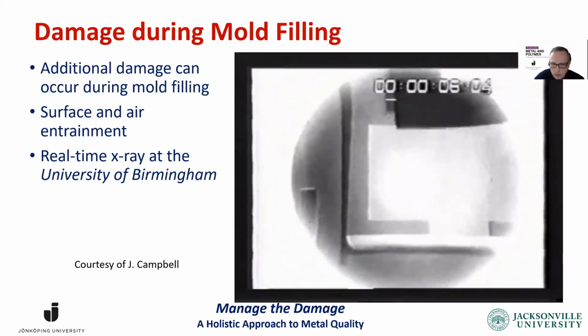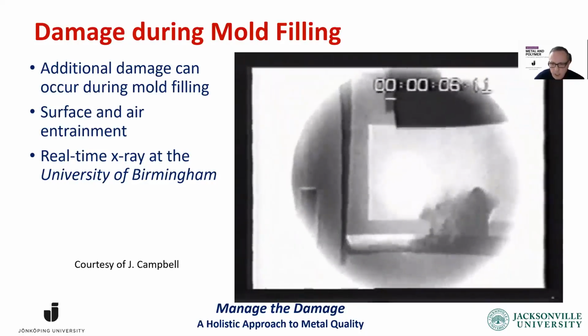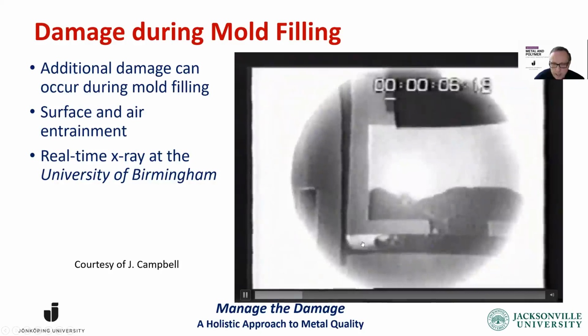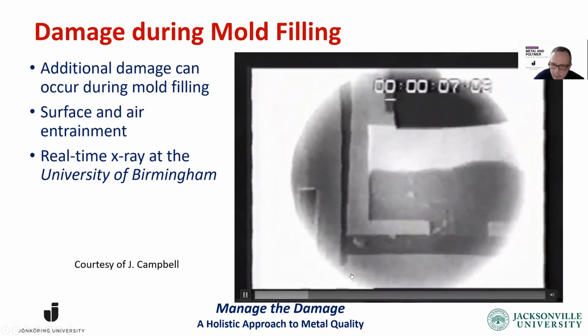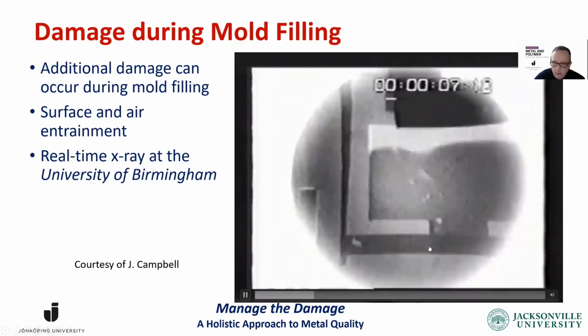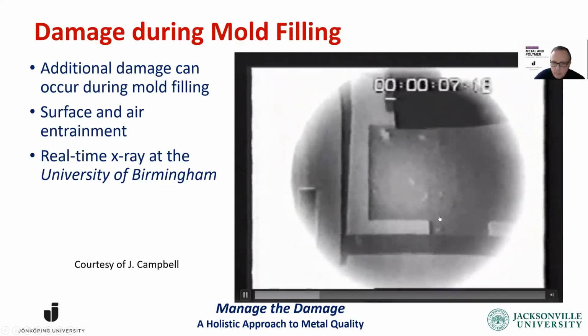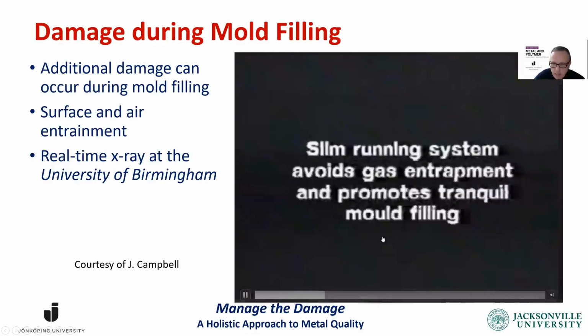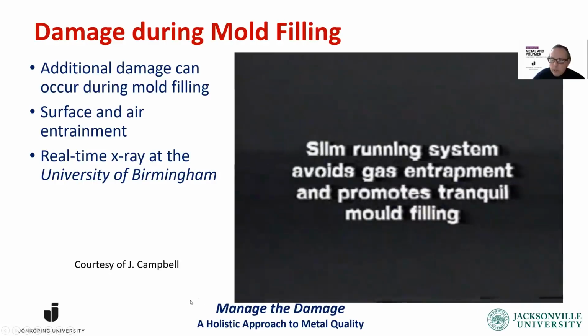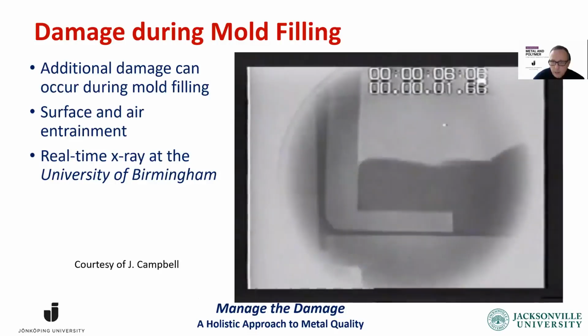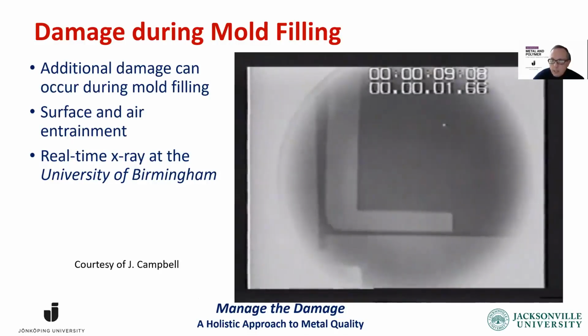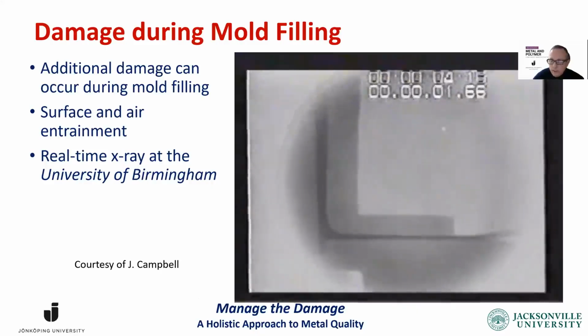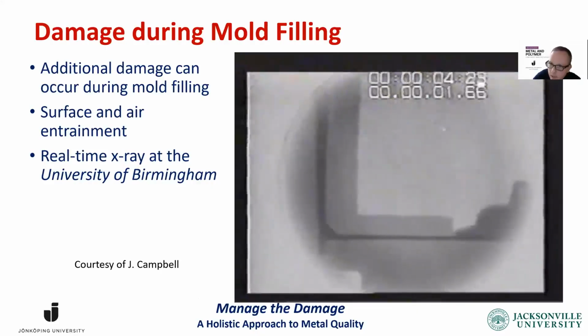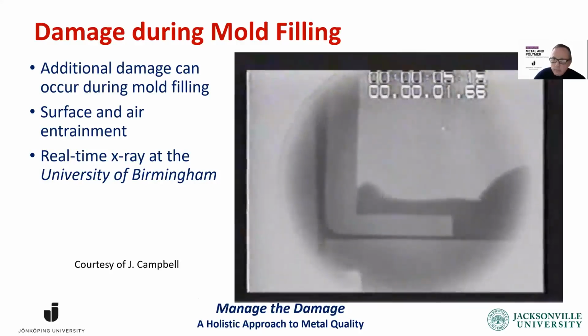This is the slow version. There's a huge hydraulic jump. Air is entrained because we have the wrong gating or filling system, and that air, of course, has buoyancy, goes up, and leaves all kinds of oxides. Some of that is left behind. But if you were using the right gating system, then air entrainment would not happen. The surface of the liquid would be kept uniform, and there would be no entrainment, no additional damage, I should say, during mold filling. But if we did all the melt transfers before, this part really doesn't matter.